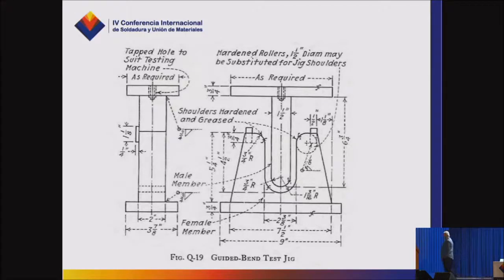Does this look familiar? Bend test fixture, same bend test fixture that we have in the code today, although it only has one set of dimensions. It doesn't have a table of dimensions. Section 9 in its early renditions only covered carbon, low alloy and stainless steels. All those materials could withstand 20% elongation in a bend test fixture, so the standard bend test fixture took your bend test specimen and wrapped it around a 2T radius. So a 3/4 inch thick specimen, you wrapped it around a 1.5 inch radius, or a 3/8 inch thick specimen, you wrapped it around a 3/4 inch radius. That put 20% strain in the outer fibers of that bend test specimen. That rule is still with us today.